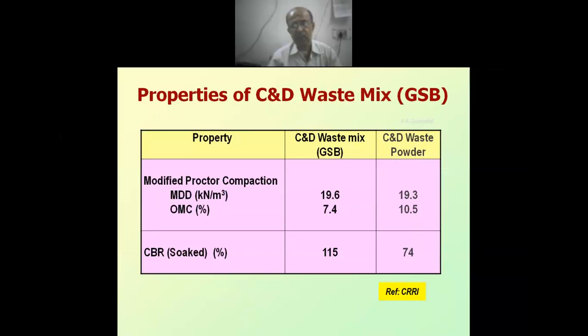Properties of this GSB mix made using the C&D waste: we tested in CRRI the MDD value and CBR value. When we intermixed these 3 materials, it has very good properties compared to C&D waste powder alone, which I put here for comparison purposes. The C&D waste powder itself had 74% CBR. When it was intermixed with some aggregate, it had 115% CBR. It's very, very high. Normally, WBM or WMM is considered to have a CBR value of 100%.